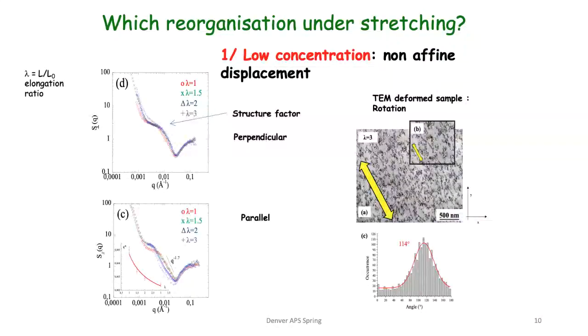And you see on the perpendicular direction that the main information, which is the Q star corresponding to the abscissa of the peak here, which is the distance between particles, is actually not deformed so much, although we vary from deformation 1.5 to a large deformation of about 3. So this should be visible, and we see nothing.